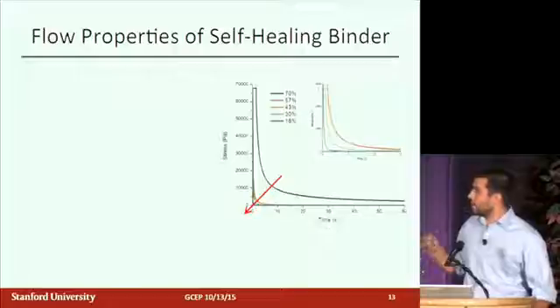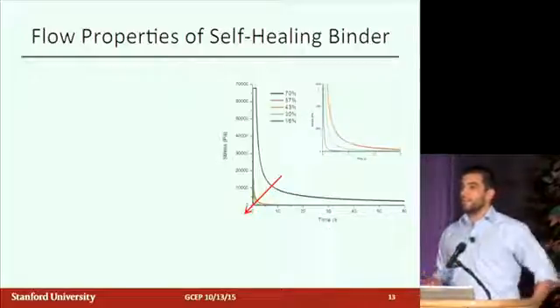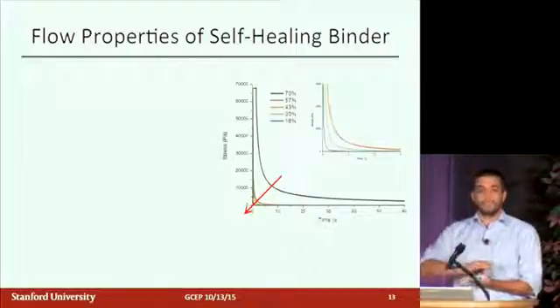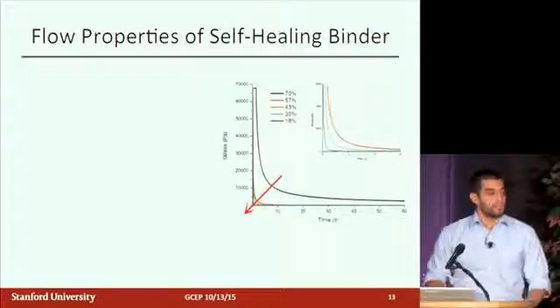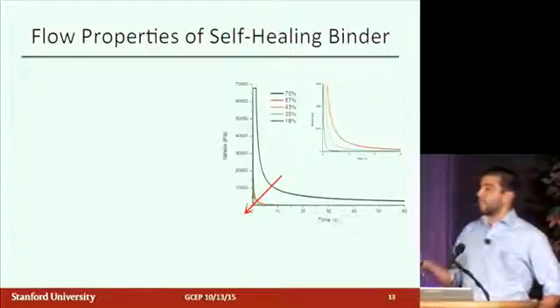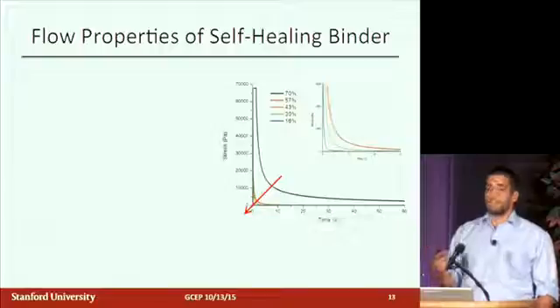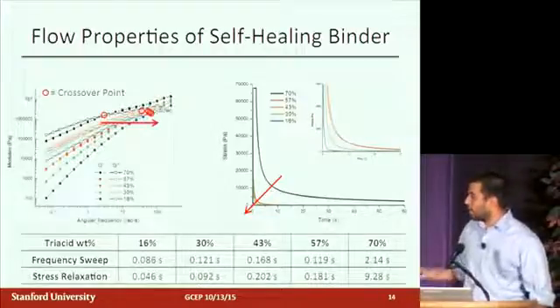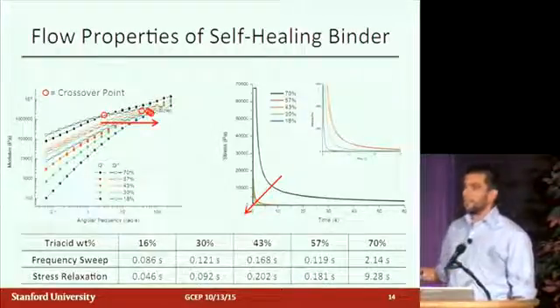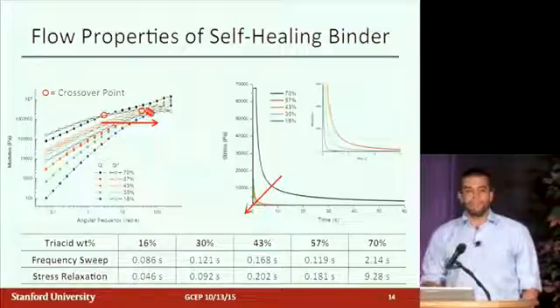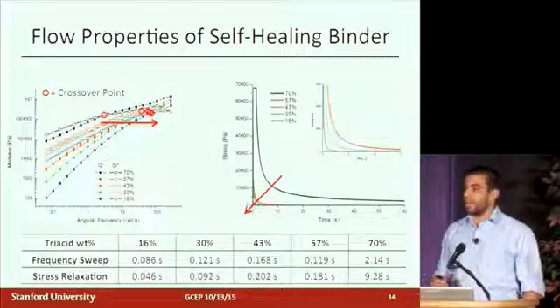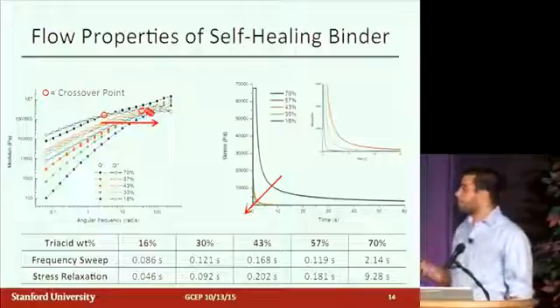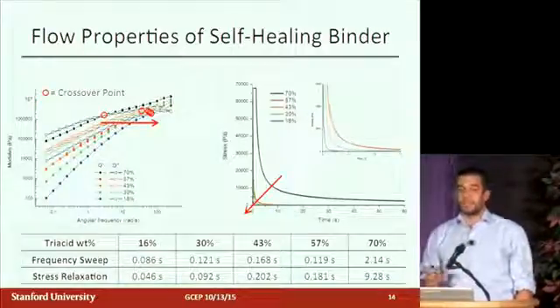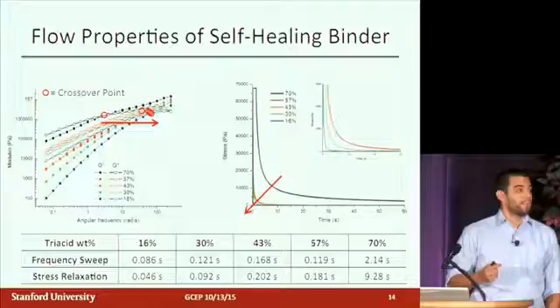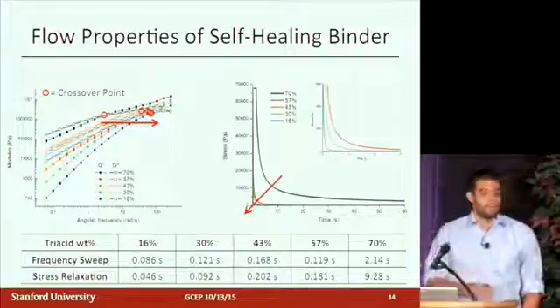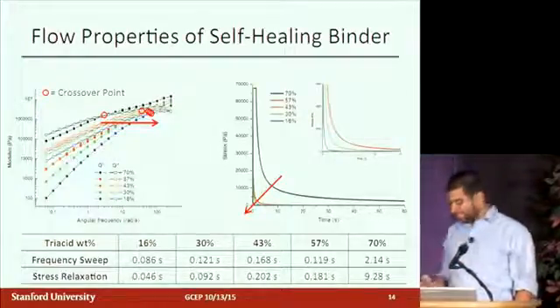The other thing we've done is a stress relaxation experiment. What you do there is instead of oscillating the plate, you just step strain and then watch as the stress decays. And again, you can use some modeling to extract the relaxation times here. What was exciting about that is 2 things. 1, the data lined up, so it was nice to know that these experiments agreed. And 2, we have materials that range over about 2 orders of magnitude of relaxation times. So the synthesis was successful, and we can actually probe what we were trying to probe, which is these different mechanical times.